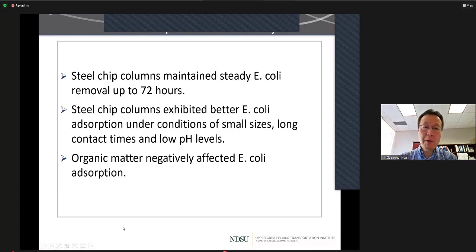So this is a summary from our column study. Steel chip column maintained steady E. coli removal up to 72 hours. So we were able to maintain steady removal over a long period. And also environmental factors could affect E. coli removal. The column exhibited better E. coli adsorption under small sizes, long contact time, and low pH levels. And also the organic matter present in the runoff can negatively affect E. coli adsorption.